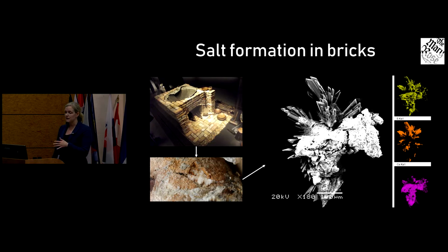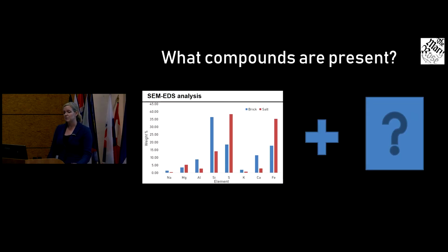These are SEM images that we took. This was a moment where I had to forget being a scientist, because when I first looked at these, I was like, wow, these images are beautiful. They're actually incredibly damaging for the material, so this is not good news, but they are beautiful images. You can see that there's sulfur and calcium and iron there. We have done some SEM EDS analysis.